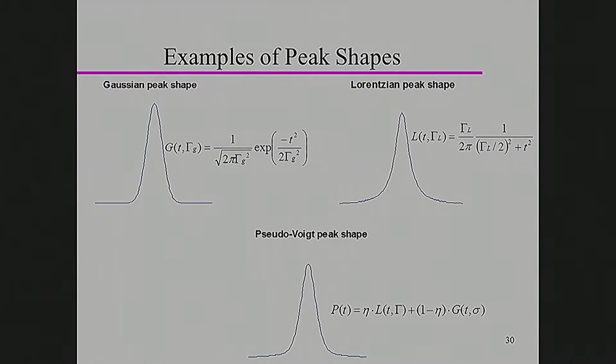Common peak shapes are either Gaussian or Lorentzian. Often neutron reactor data and X-ray lab data are described with Gaussian or Lorentzian peak shapes. Many programs use a so-called pseudo-Voigt. A true Voigt would be a convolution of a Gaussian and a Lorentzian.